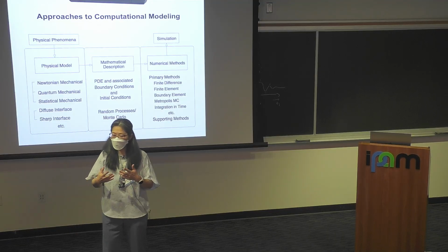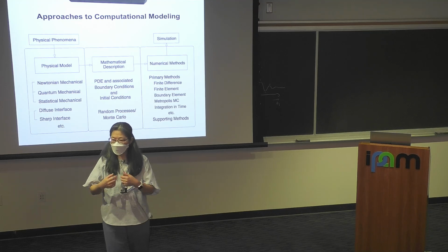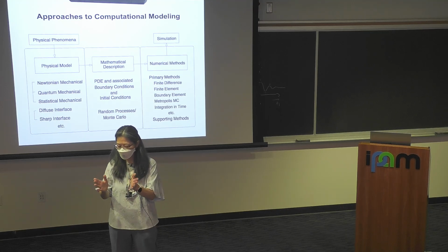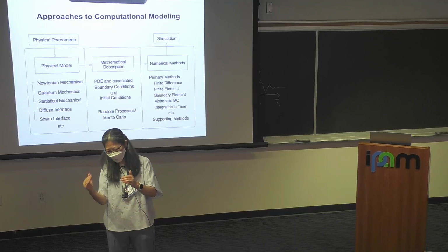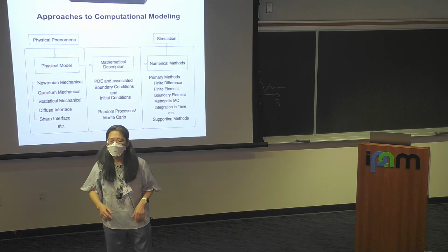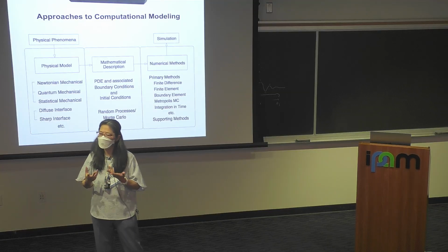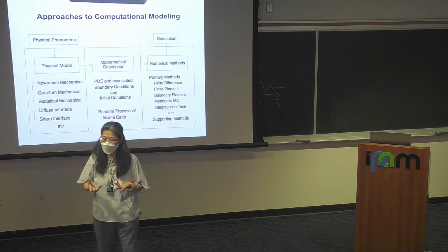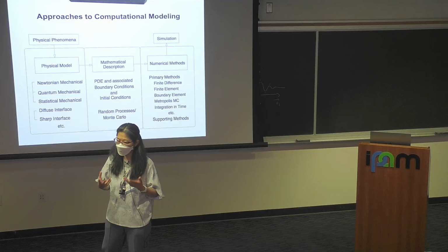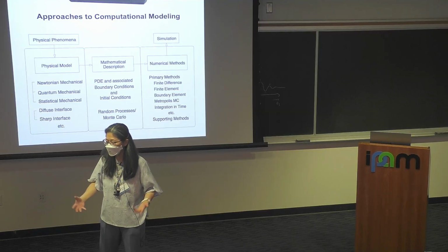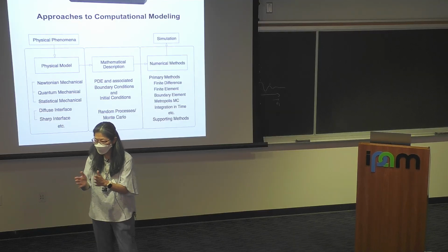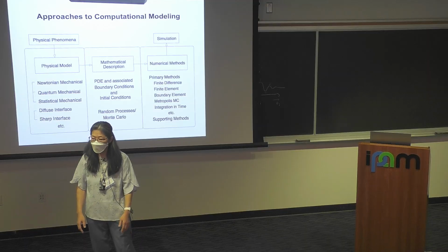And during that phase separation process, if you start in the spinodal region where it's like a bump, like here, what happens is that you have a diffuse interface, and it could remain diffuse depending on the parameter. But if it's not too quenched, then you'd have a well-defined thickness of the interface.